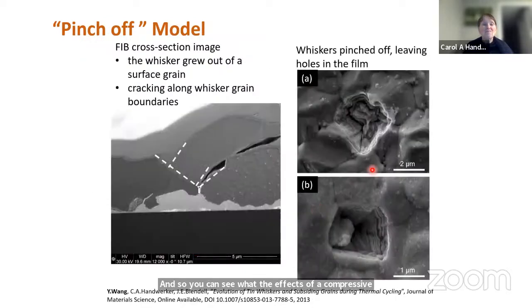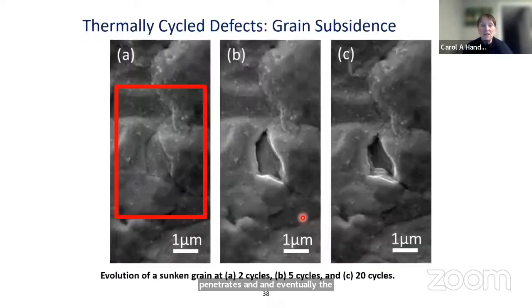And in the end, in this case, you see that there was grain boundary grooving on one side, but not on the other side. This is a FIB cross-section of the whisker growing up. And you can see the holes that formed, which again with each of these corresponds to one of the thermal cycles here and here, as the grain boundary groove penetrates and eventually the whiskers become so fragile that they break off.